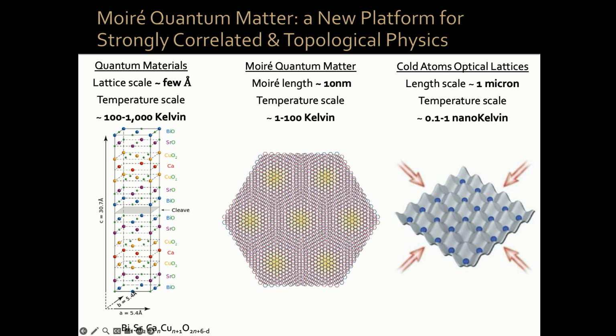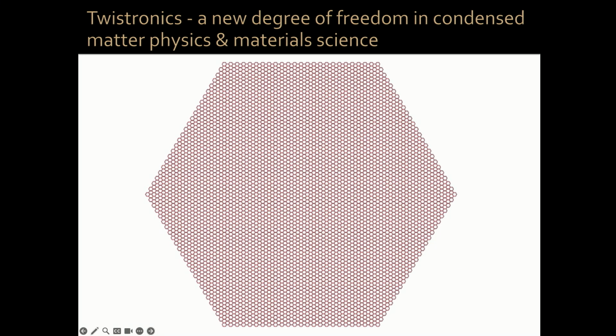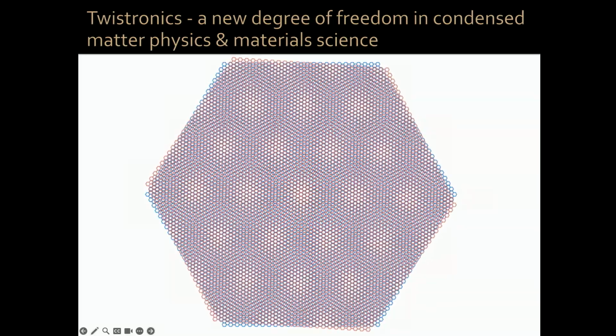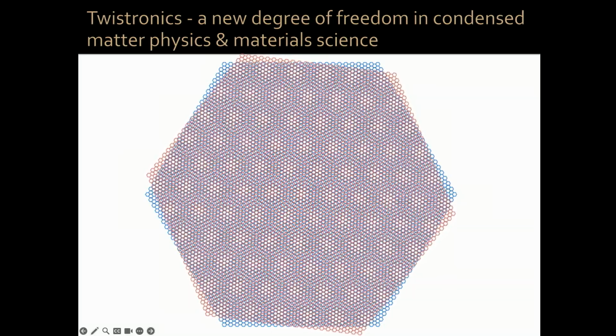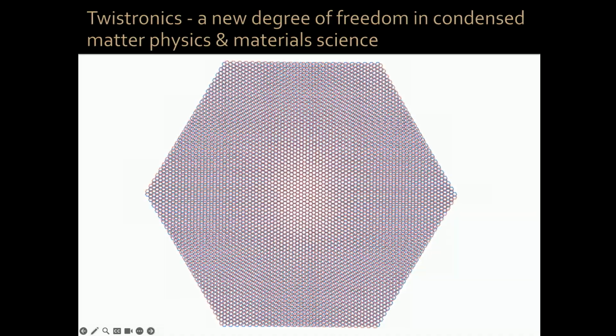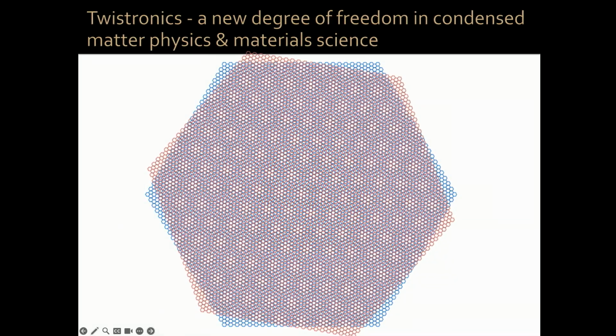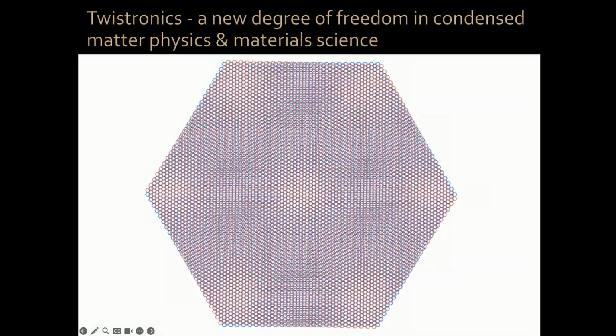So initially, the thing that enabled this Moiré quantum matter platform is the fact that when you have 2D materials, you can do something that was impossible to do in the history of material science before. You can control the relative rotation angle between crystalline planes completely at will. So for example, I can take a sheet of graphene, which is a honeycomb of carbon atoms. I can put another sheet on top with any angle of rotation between the 2 crystalline planes. Usually, thermodynamics, physics, chemistry tells you what the angle between planes should be in a structure. But now with 2D materials, I can put them on top of each other with any angle that I want. Yeah? I choose that angle.